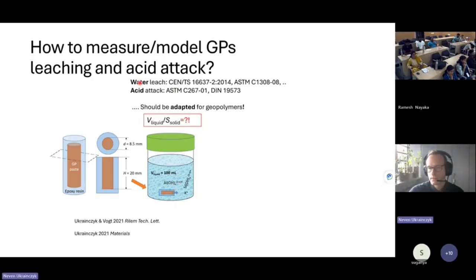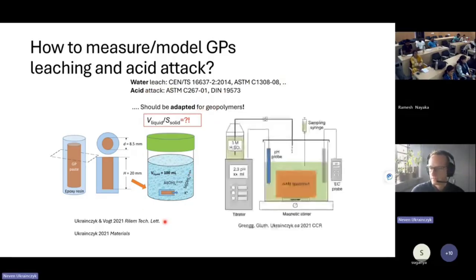So there are no standards for this. There is a water leaching test for concrete, also a standard for acid attack of concrete, but for geopolymers they should be adapted, and this is my proposal here in these papers. We also did this for acetic acid. There was a titration for sulfuric acid, because it's a strongly dissociating acid, so you need to dose it. Acetic acid you don't need to dose because it's always buffering.